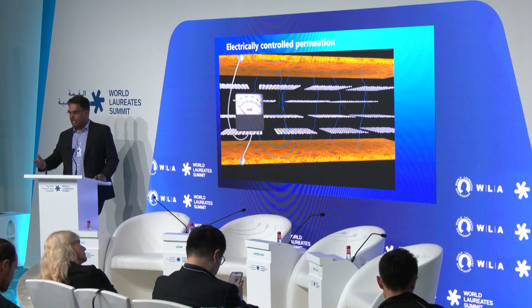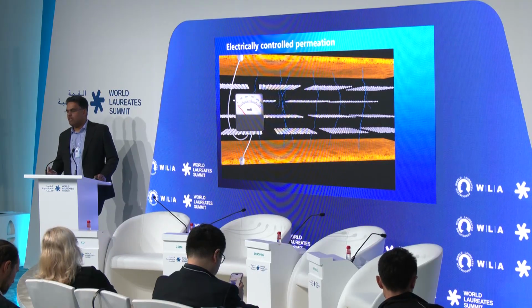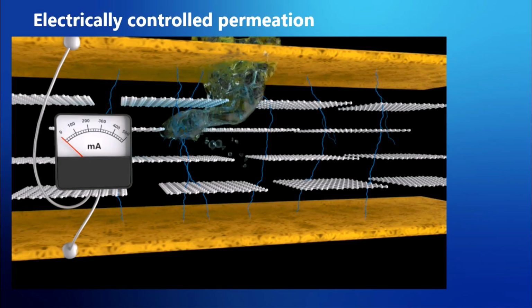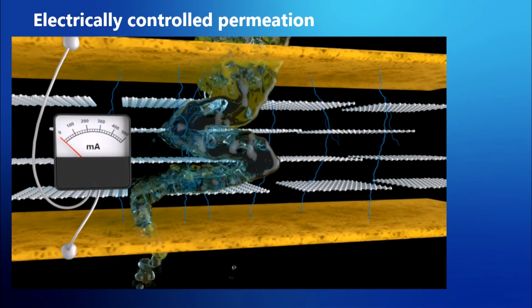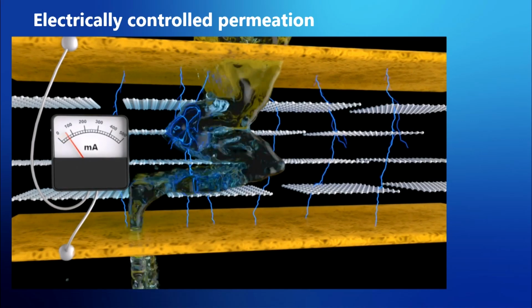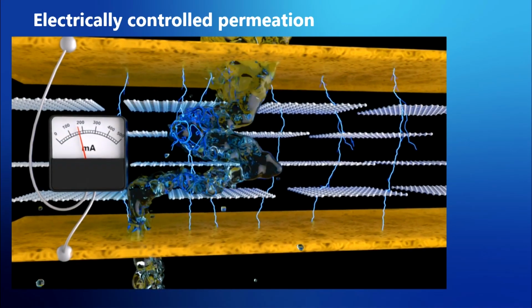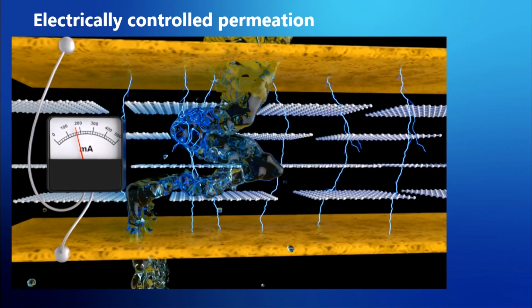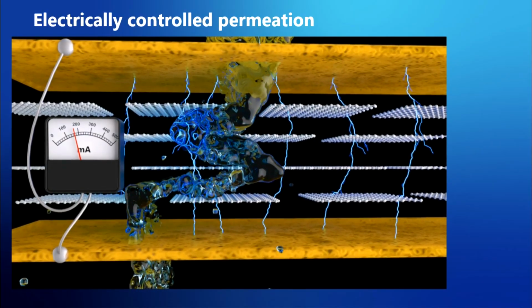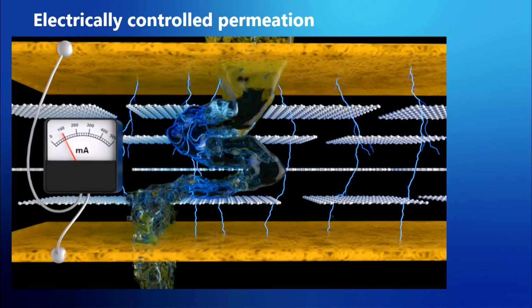So these all are comparisons of the graphene membrane with the existing membrane in terms of performance. We are improving the performance, improving the lifetime and so on. But with graphene-based membranes, we can do much more than what commercial membranes can do. In terms of a long-term perspective, this is a concept we published several years back on a smart membrane. We can make a graphene-based membrane electrically conducting by creating certain conducting filaments, and by controlling the current through such a membrane, we can make it a smart membrane.